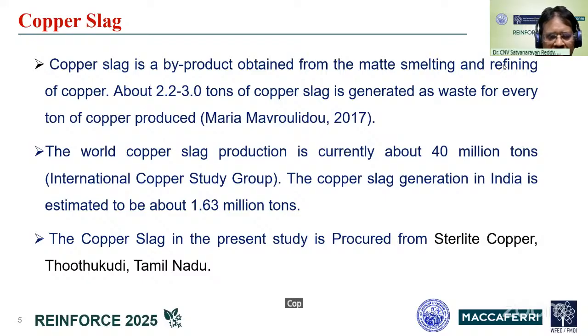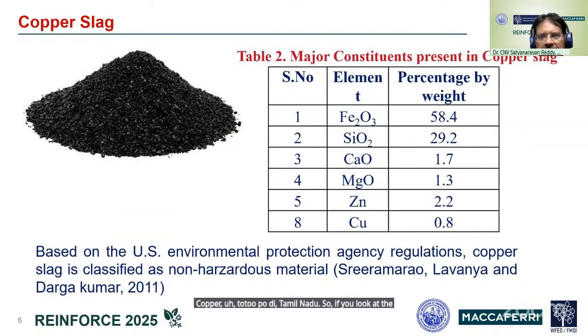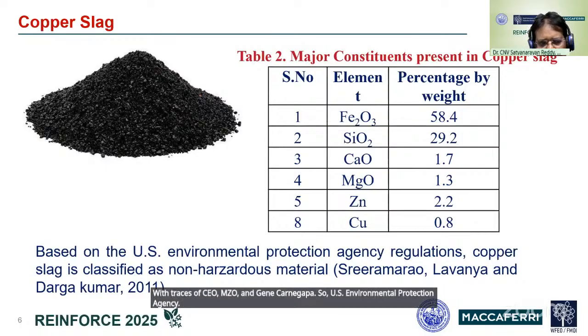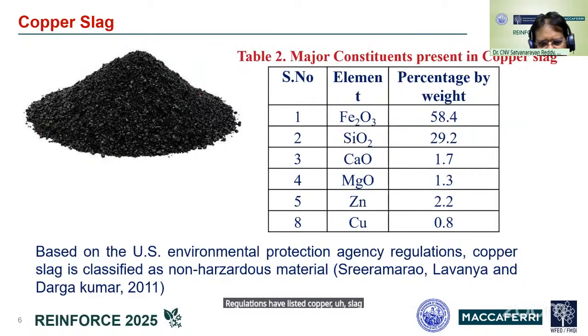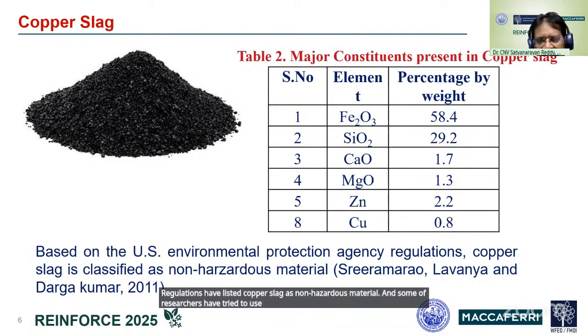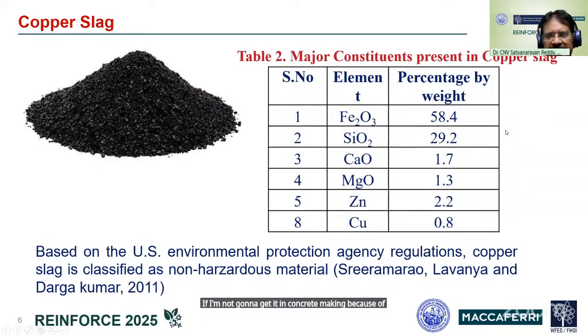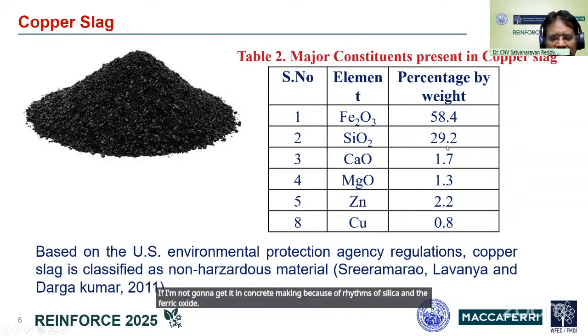copper, Thoothukudi, Tamil Nadu. So if you look at the constituents present in copper slag, it is containing ferric oxide of 58.4% and silica of 29.2% with traces of CaO, MgO and zinc and copper. So US Environmental Protection Agency regulations have listed copper slag as non-hazardous material, and some researchers have tried to use copper slag as substitute to fine aggregate in concrete making because of presence of silica and ferric oxide. So it is a granular material.